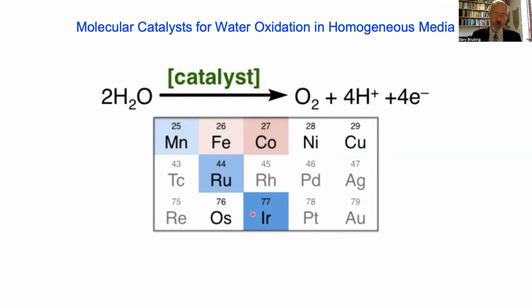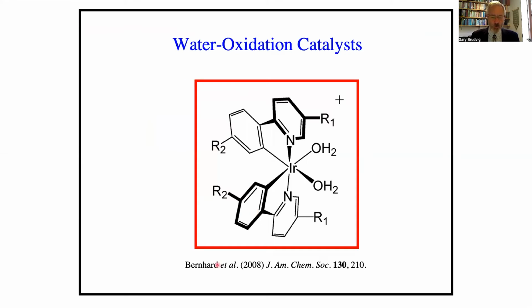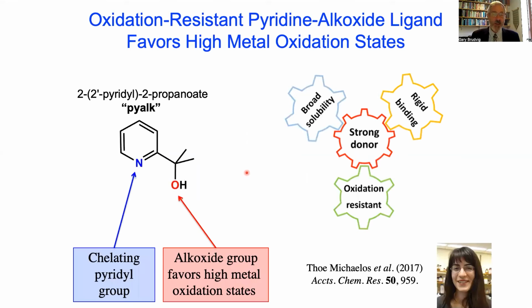Of course, it's been known for many years that iridium oxide is the best oxide catalyst, but it's only relatively more recently that molecular iridium complexes have been studied. And the first report was by Stefan Bernhard in 2008, with phenylpyridine iridium complex. And we've worked to achieve a complex with high stability and also high catalytic activity. And we found this chelating ligand, we call it PyAlk, or the pyridine and alkoxide groups, is really a winner.